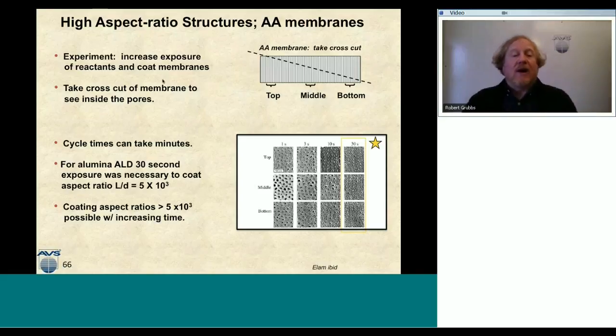So let's take a cross cut of that. And so here's the data from that. You can see that here are the pores imaged at the top for 1, 3, 10, and 30 seconds of time for exposure. Here's the middle, and here's the bottom. Notice at 1 second exposure, the middle is not coated as well as the top.